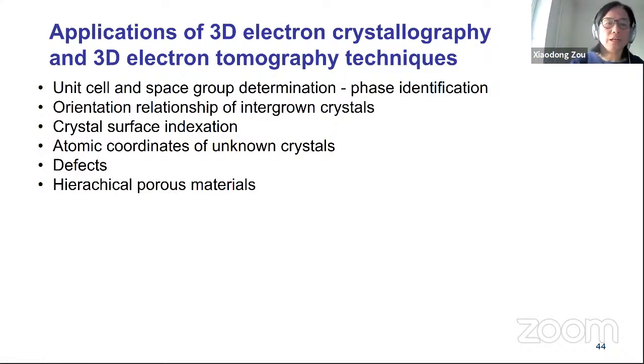Perfect. Okay, sorry. So this is a summary of the applications of using electron crystallography and electron tomography techniques. We can use them for discovering new materials. If you don't know the material, we can determine the unit cell and the space group. In this way, we are able to make phase identification of the material, and if the material is unknown, we are able to solve the structure. We can also use electron diffraction to determine the orientation relationship of intergrown crystals, and also the crystal surfaces and index them. And we can also study defects and hierarchical porous materials.